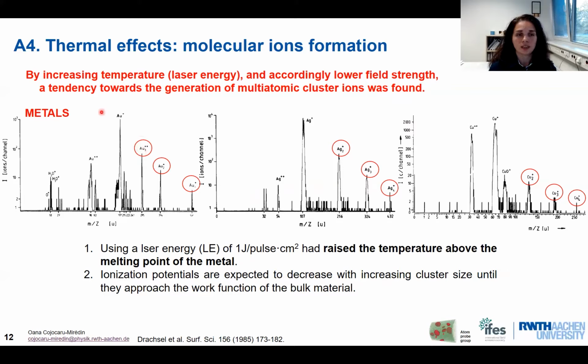And they show nicely this for three different metals, gold, silver, and copper, that on the mass spectra we have the formation of Au3, Au2, or Au4 molecular ions. And the same goes for the silver and the copper. And the only explanation for that was that the laser energy was so high that it had induced a very high increase of the temperature, a temperature above the melting point of the metal. And this is how they explain the formation of these molecular ions.